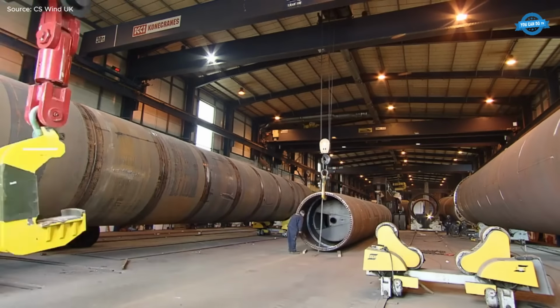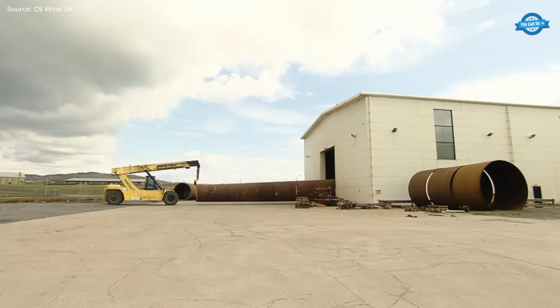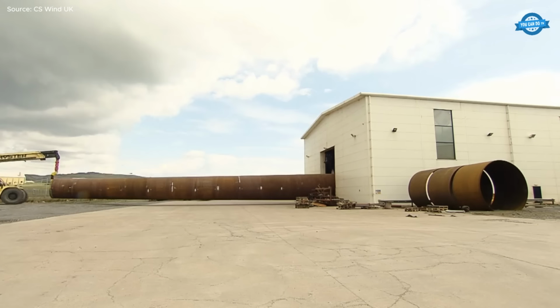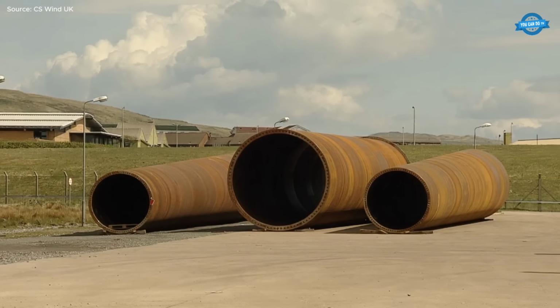Surface treatment is critical. The sections are grit blasted to a controlled roughness, then coated with a multi-layer protective paint system: zinc-rich primer for corrosion resistance, intermediate epoxy layers for barrier protection, and a durable polyurethane topcoat for UV and weather resistance. Completed tower segments, often weighing dozens of tons, are then transported for final erection at the wind farm site.